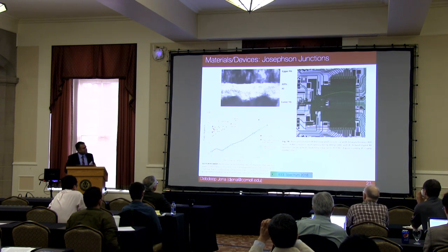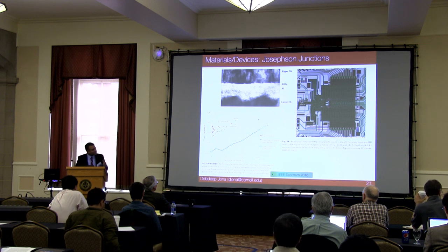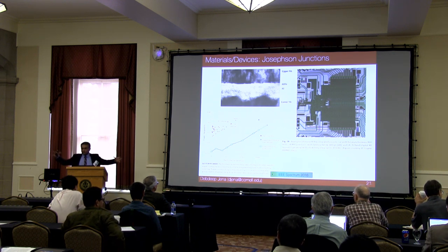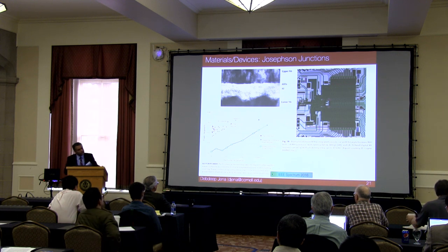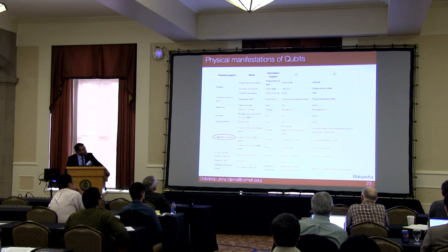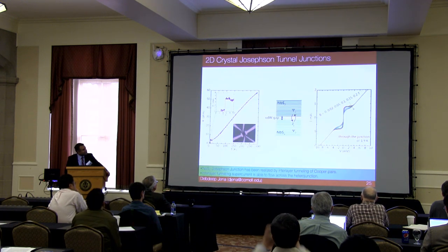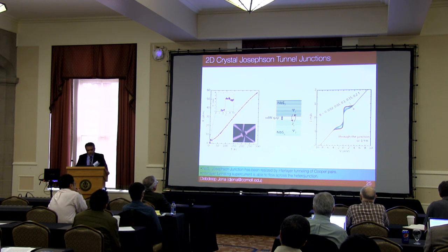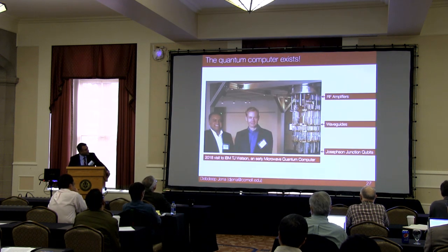So in a joint effort with NRL, and in our group we also do molecular beam epitaxy, we started growing these structures. Can we integrate the superconductor with the semiconductor and take advantage of what each has to offer? So this is a niobium nitride layer grown epitaxially with aluminum nitride or with GaN. It indeed is superconducting. On top of the superconductor, we can continue growing.